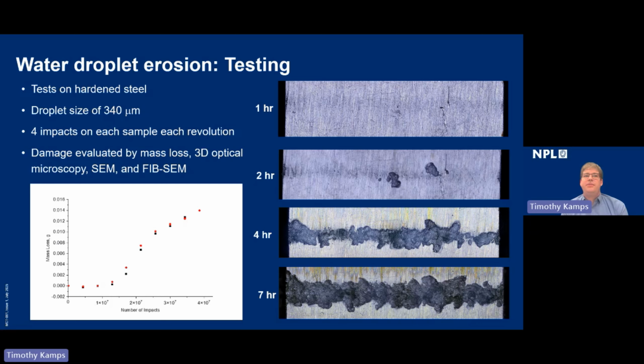At the bottom left, you can see a characteristic curve for a sample that's been exposed to water droplet impingement. This starts off with a period of no mass loss. This is the incubation period, where crack networks and stresses are formed inside the material before we reach a period of maximum erosion. Shortly after that, we reach a period of steady state condition. And this graph and the identification of these 3 regions are where this test allows differentiation between different materials.